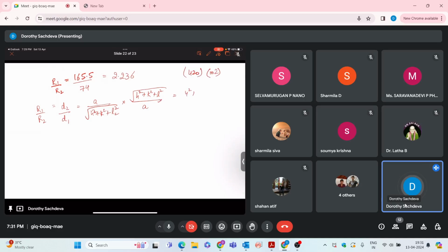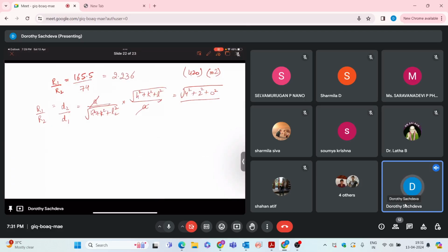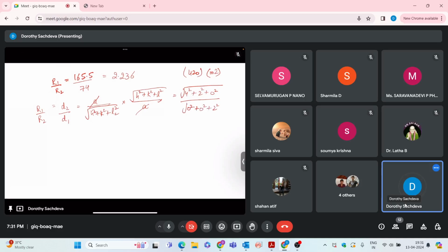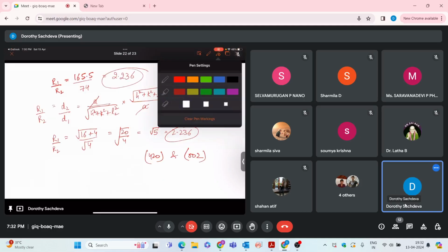So for 420, 4 square plus 2 square plus 0 square whole under root, the a will cancel out. And the next will be 0 square plus 0 square plus 2 square. So this R1 divided by R2 will become 16 plus 4 divided by 4, whole under root. So this will be 20 divided by 4 whole under root. This will be under root 5, and under root 5 value is 2.236. So this also confirms that your planes are 420 and 002 according to the given R values, which are 165.5 and 74. And also you can confirm them using your cos theta value.